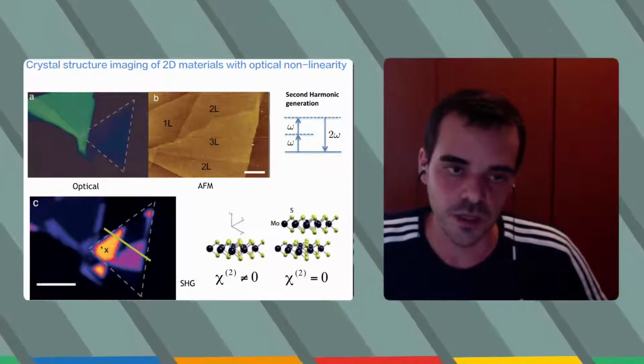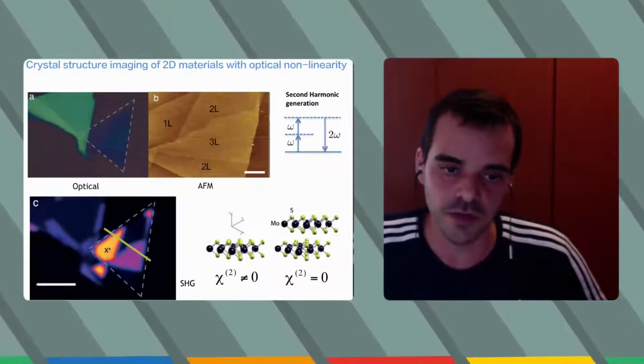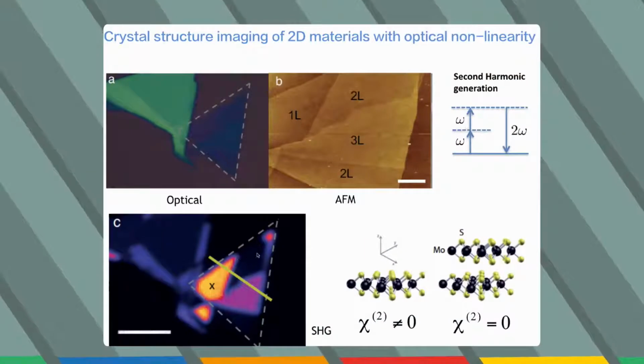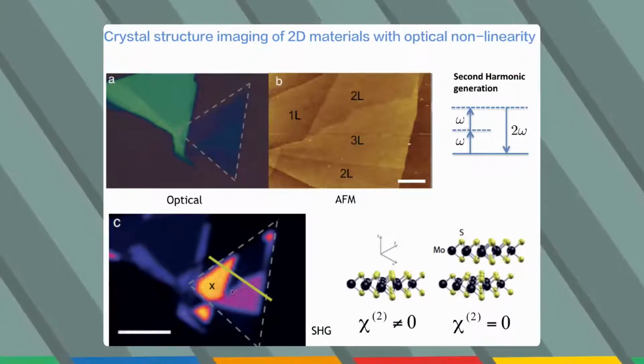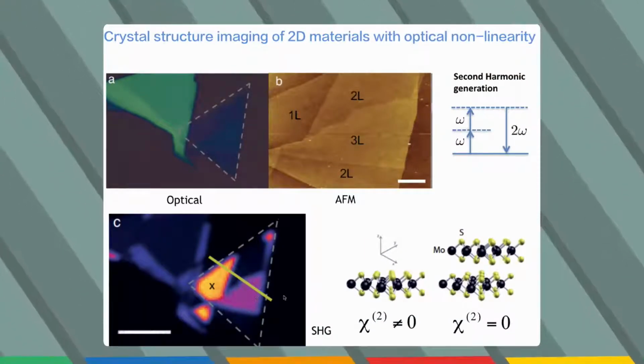So we can see that for the monolayer part, we have a very strong second harmonic, and for the 2-layer part, we have no second harmonic, and for 3 layers, we have second harmonic again.